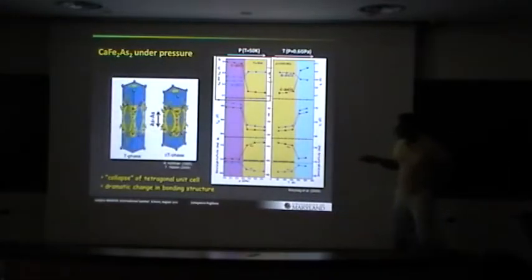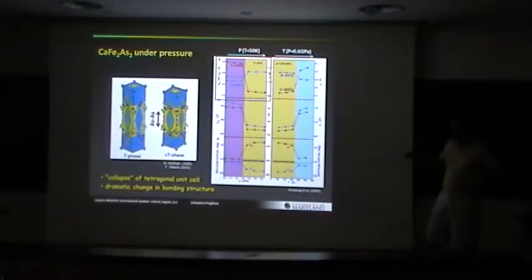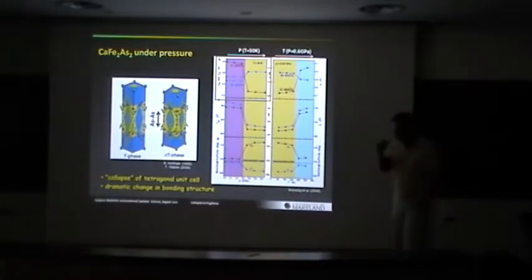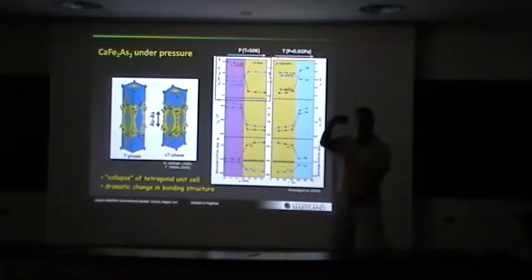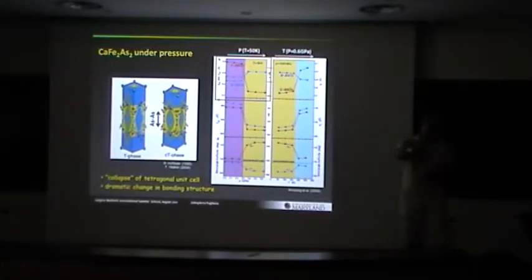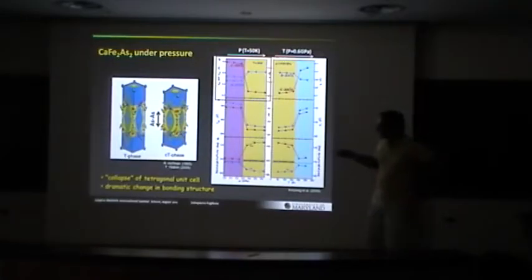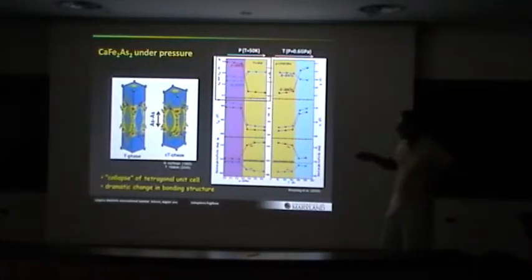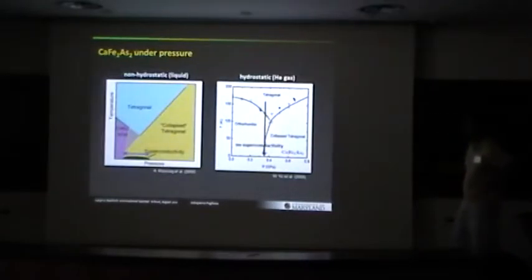Okay, I'll get to this later. We have some evidence now that directly indicates that this collapse is simply caused by the fact that the interlayer arsenic atoms decide to bond once they're close enough. So the p orbitals overlap and they hybridize in some way, and they form a bond that's preferred once these guys are close enough. Okay, I'll get back to that.